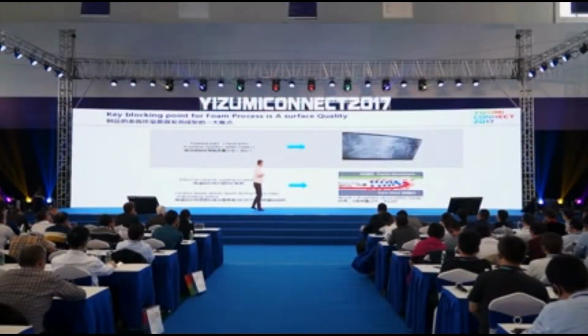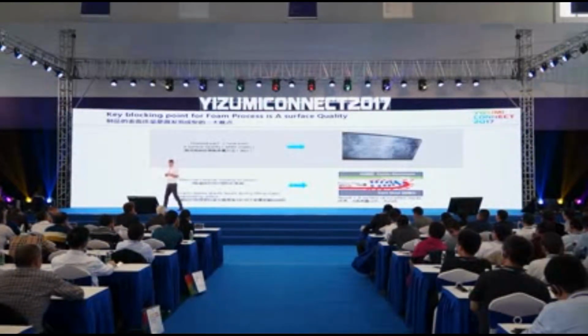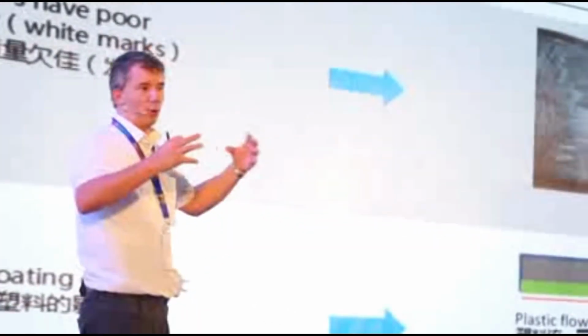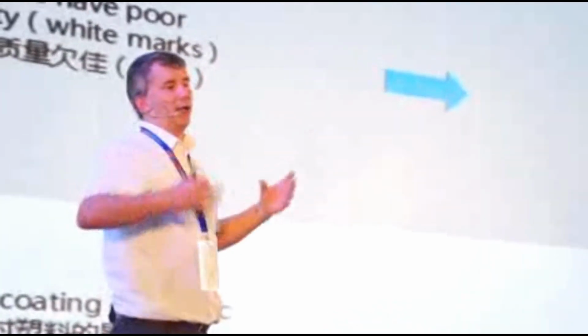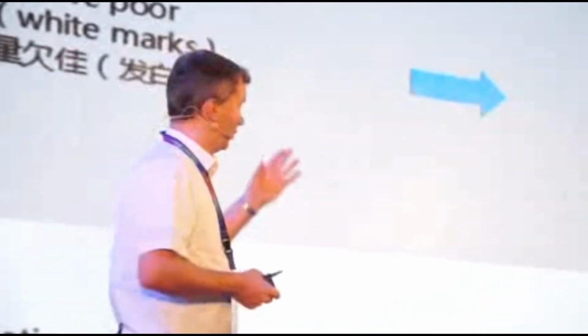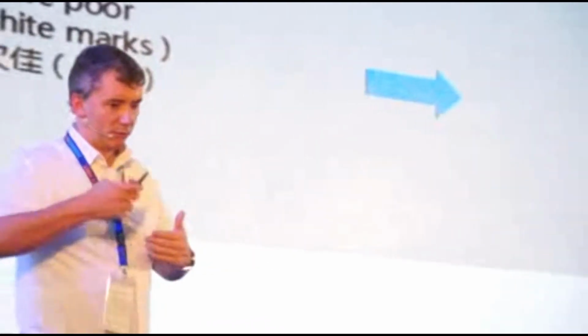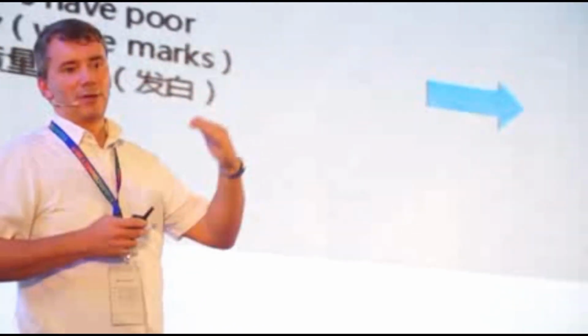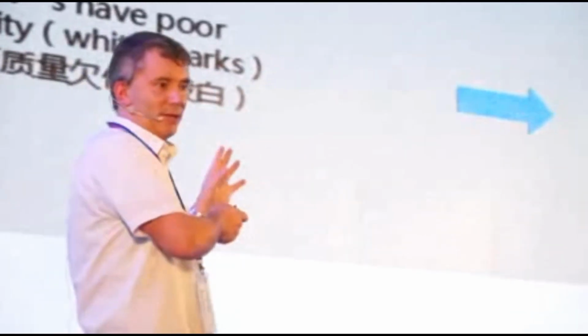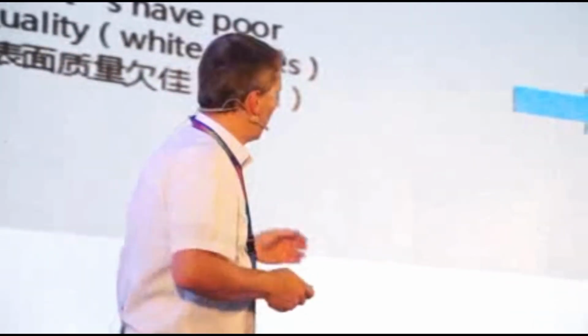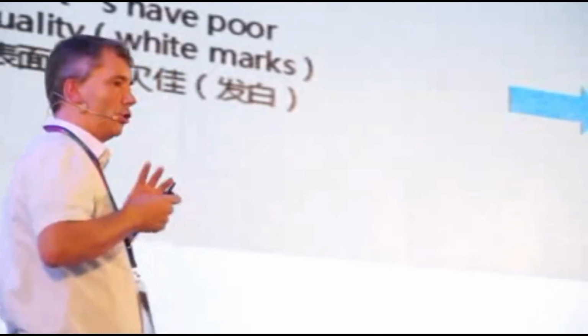So we have actually had products that we have put on with this technology, graining, and the quality is amazing. I mean, it really is very high quality. So we know now we can solve that A surface quality issue, and if we are mainly focusing on polypropylene large parts, this is where we get a big maximization of the aluminium and the ceramics. You know, if you tried to use glass-filled nylons and this, it would damage not only the mold, but the ceramic itself. But PP is a huge market.